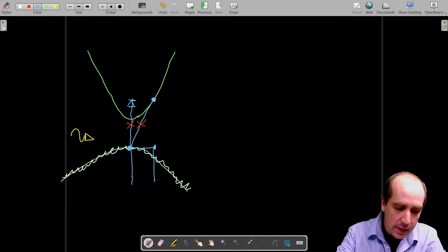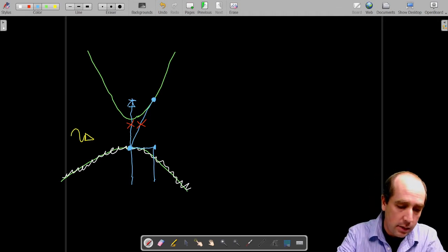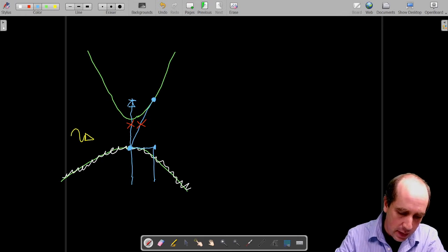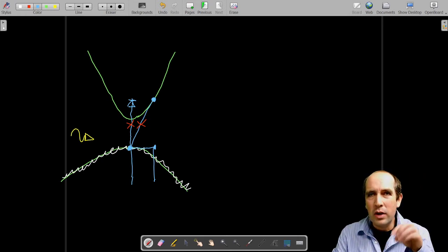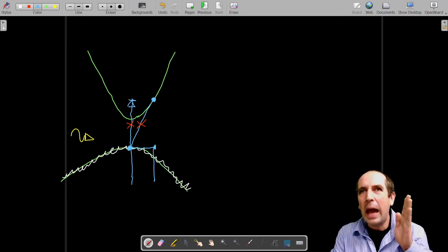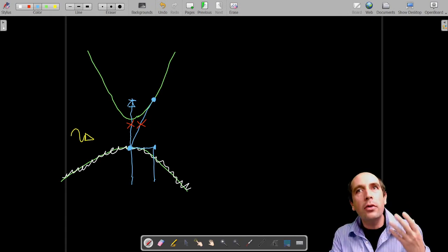Therefore, the only transitions that can happen in this context are transitions that happen vertically. So this means that the electron will start and finish with a state that has the same momentum. Okay, it can change a little bit, but we're talking about 1% or maybe even under 1%.